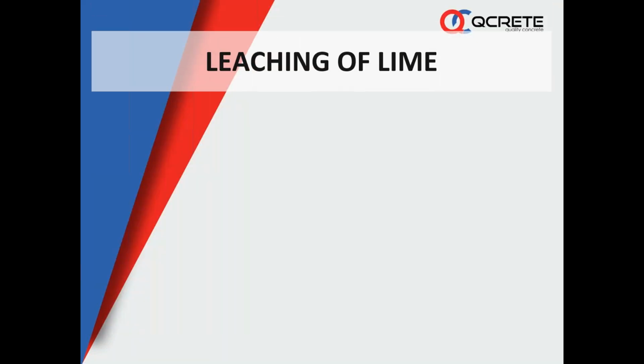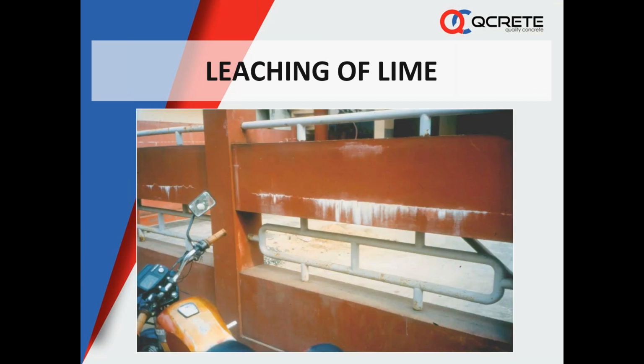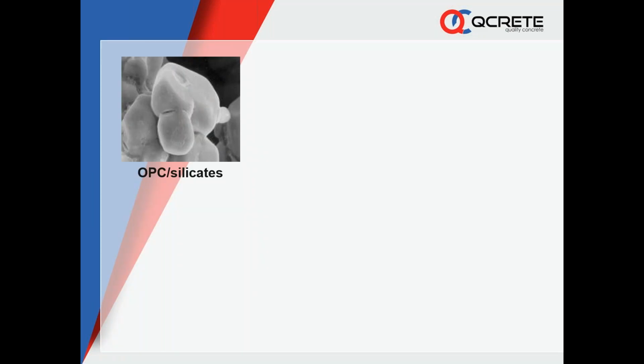I will come to that. You can see here one particular structure, a handrail. Through the capillary pores the moisture has entered, and the unhydrated cement comes out as leaching. The white patches which are seen are all unhydrated cement particles inside the concrete body, which react with this moisture and come out, leaving bigger capillary pores inside the concrete body. The next time moisture enters, the crack widens and it reaches the steel.